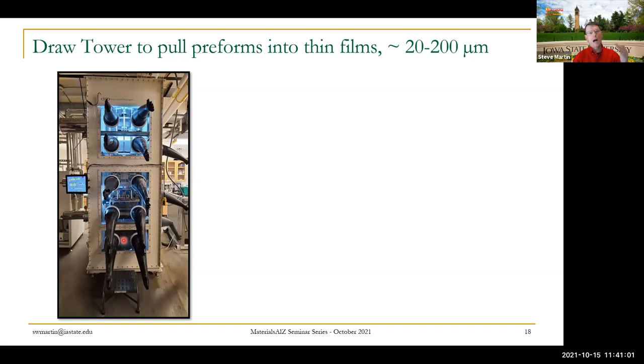Our glasses nominally, as I showed, are stable in air, but even if they're stable in air, we would still pull them inside a glove box. If you're pulling a 20 micron thick film, a 10 micron or 100 micron dust particle would be catastrophic. So this is also to keep dust down and keep the films clean.